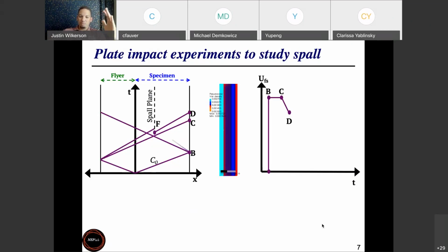And so that material that's being compressed at the highest pressures is moving the fastest. And so it will catch up to the material that was loaded first, and then it can even overtake it. And that's what can give you a very sharp single shock wave in compression. So that's why on the XT diagram, I draw it as just one line, because in an idealized sense, it's happening almost instantaneously. And then on this diagram on the far right, it's almost vertical because it's happening almost instantly. This is still a little idealized.